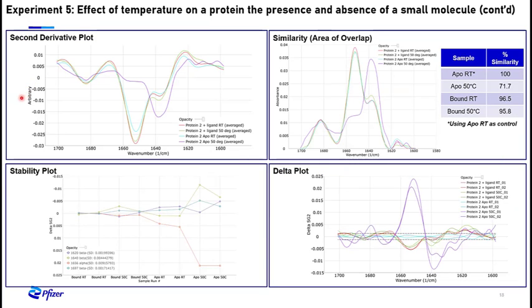The second derivative plot from experiment 5 shows that the apo protein at room temperature and the ligand-bound protein at both temperatures have retained most of their alpha helicity, while the apo protein that's been heated to 50 degrees has almost no alpha helical structure left and is primarily beta sheet, suggesting this sample has surrendered to the heat stress and is most likely aggregated. To the right, the similarity plot shows this a bit more clearly.